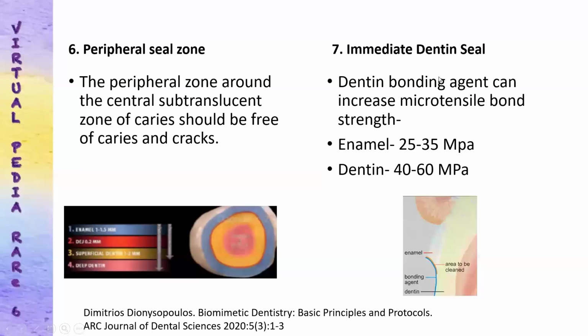The next thing which is important to increase the bonding strength is the immediate dentin seal. As discussed, immediate dentin seal means that we are applying the bonding agent on the dentin and we are removing the bonding agent from the enamel. The care should be exercised that the bonding agent should be limited till the dentin only without coating the enamel. This will help us to increase the bonding strength by 40 to 60 megapascal.